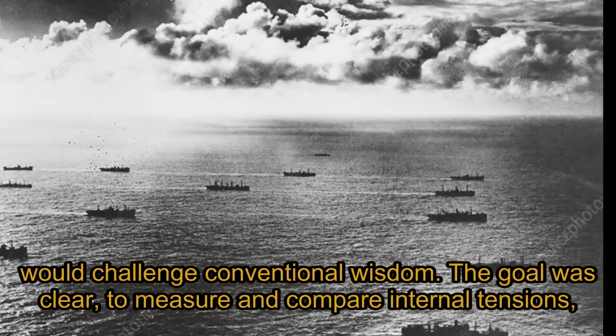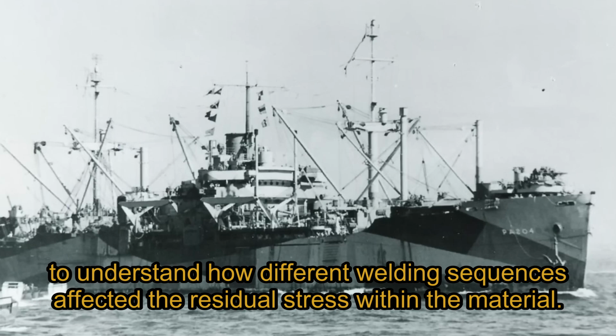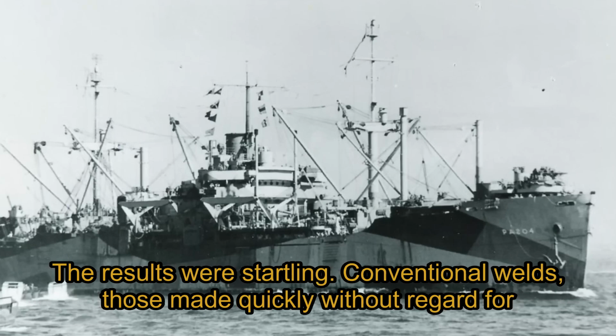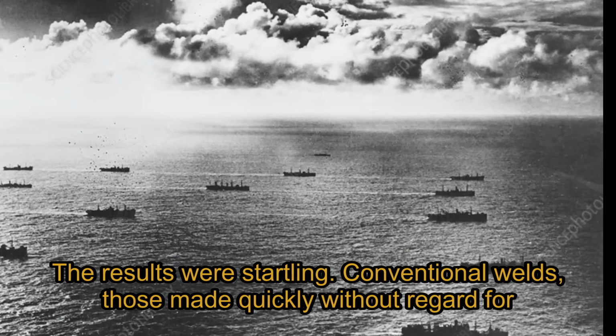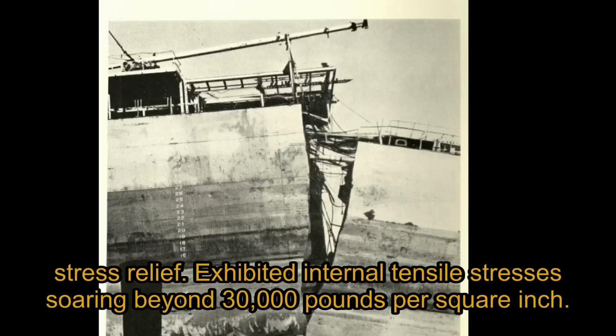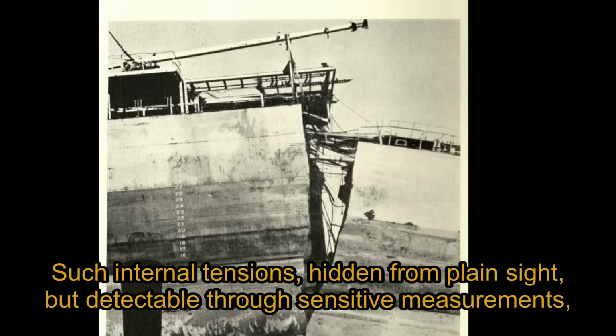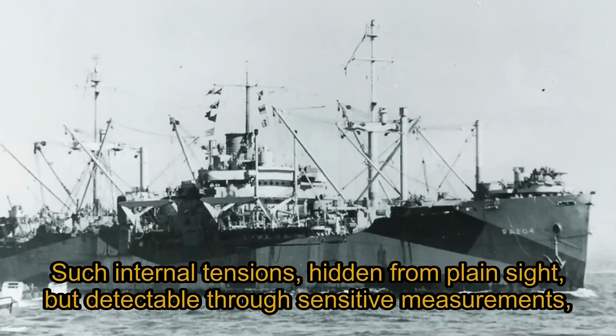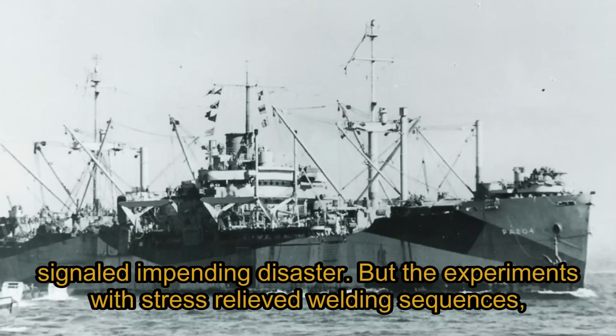The goal was clear: to measure and compare internal tensions, to understand how different welding sequences affected the residual stress within the material. The results were startling. Conventional welds, those made quickly without regard for stress relief, exhibited internal tensile stresses soaring beyond 30,000 pounds per square inch. Such internal tensions, hidden from plain sight but detectable through sensitive measurements, signaled impending disaster.